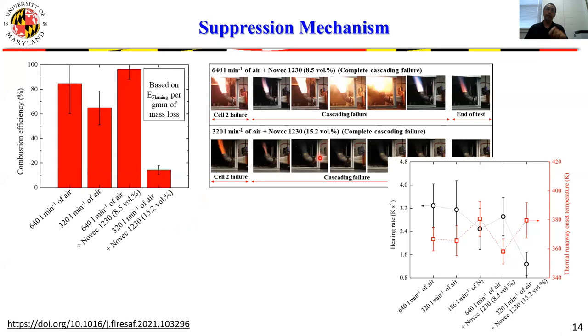So when Novec 1230 was delivered at a constant flow at 15%, we found that the mixtures that are formed from the battery decomposition products and Novec 1230 did not reignite upon exit and re-entry to the atmosphere. We also were able to suppress cascading failure itself, the thermal runaway propagation from battery to battery, in about 60% of these tests, which is rather significant. So not only were we able to suppress flaming combustion, we also were able to suppress thermal runaway propagation.